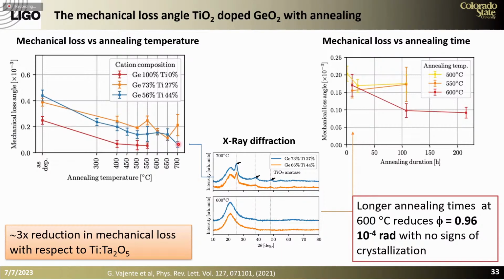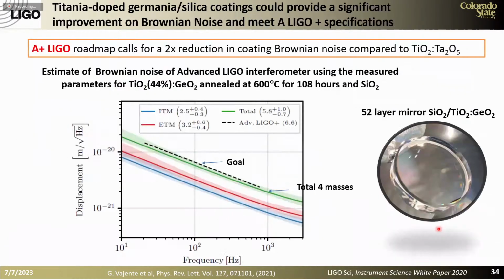And in fact, we have done several other studies in which we play with the length of the annealing and the temperature. And when we go to very long annealings and a temperature of about 600 degrees C, we get films with a mechanical loss that are of the order of 3 times lower than titania doped tantala.